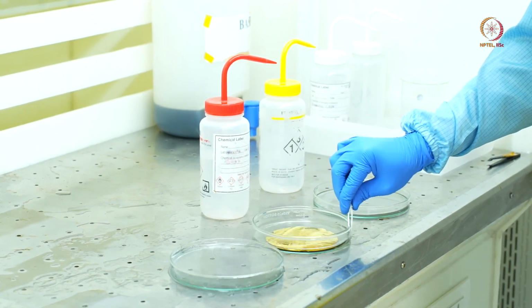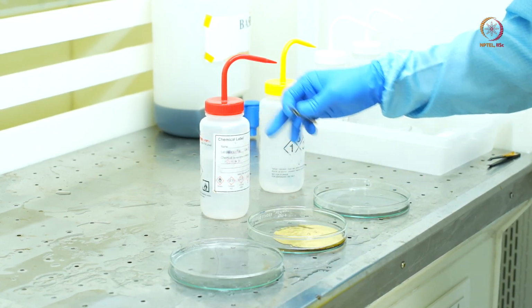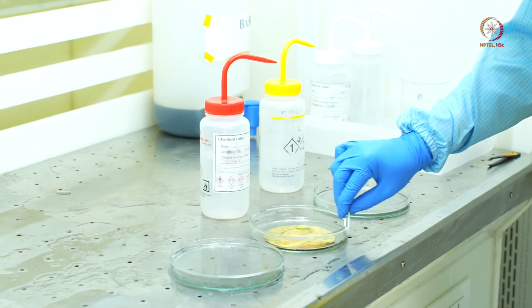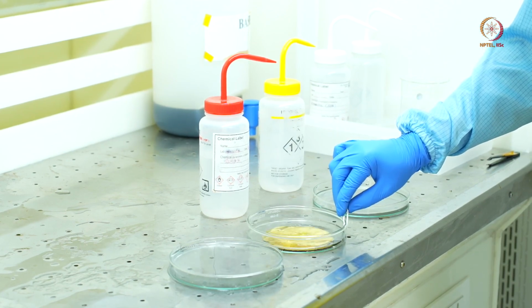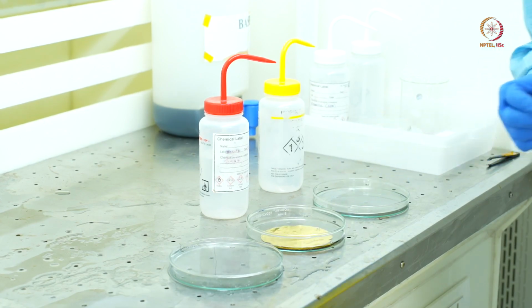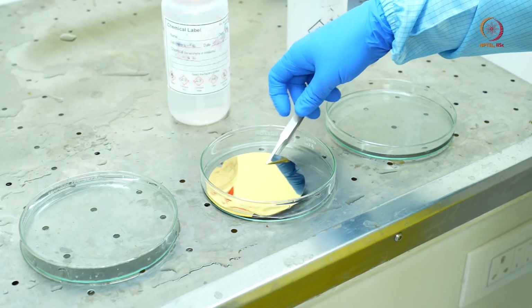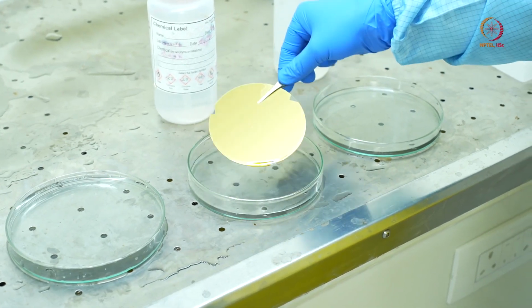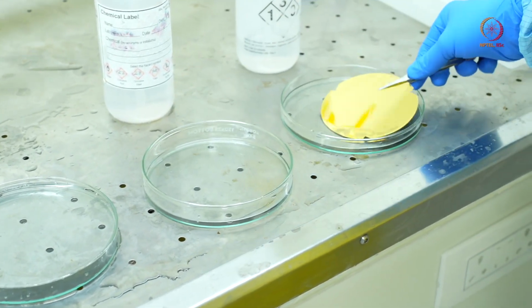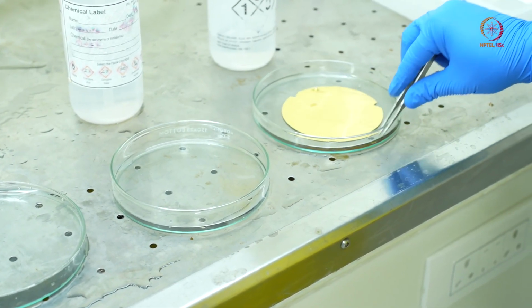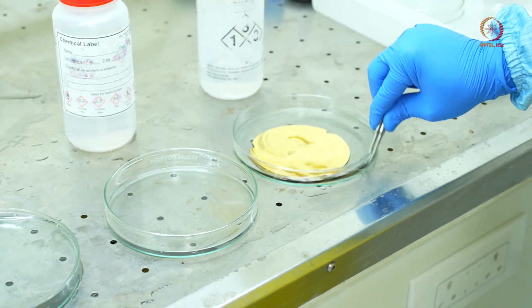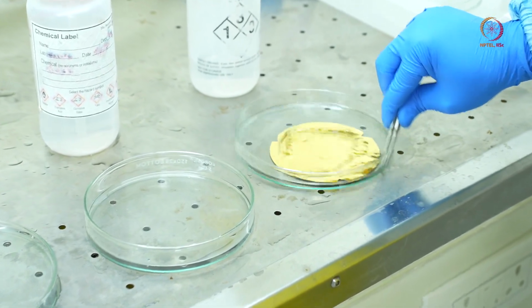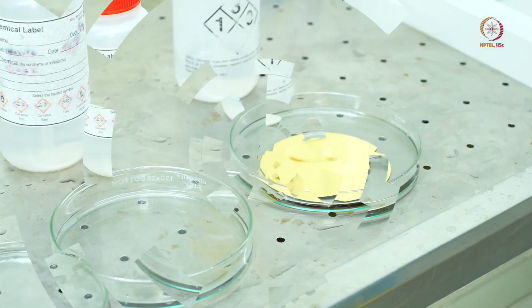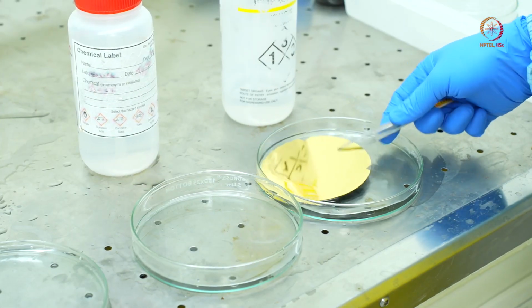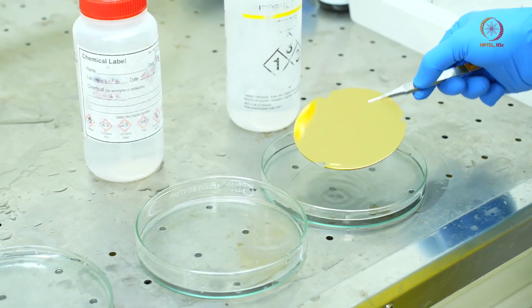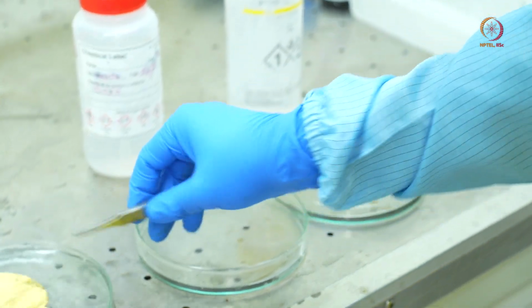So we have a glass petri dish with acetone here. You can see the acetone bottle here. Okay. So let us leave it for 5 minutes here for cleaning in acetone. 5 minutes is over. So I am removing the sample from acetone and moving it to IPA here. Isopropyl alcohol. So let us leave this also for 5 minutes.